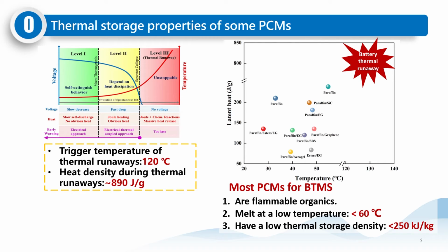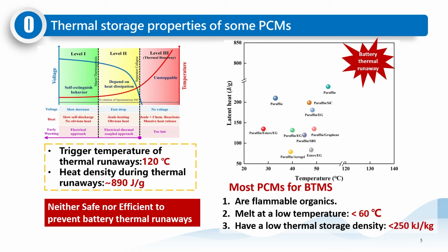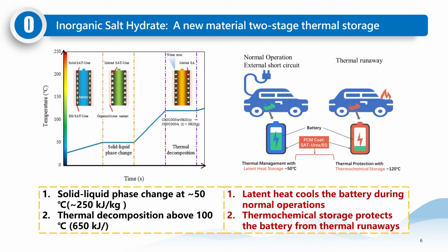And third, most of the PCMs, their thermal storage density is limited below 250 kilojoules per kilogram. So it is also much lower than the heat density of the battery. Based on these conditions, we can conclude that the PCMs we use now are mostly neither safe nor efficient to prevent battery from thermal runaways. And so we here propose a new strategy.